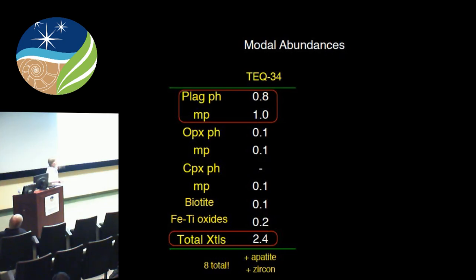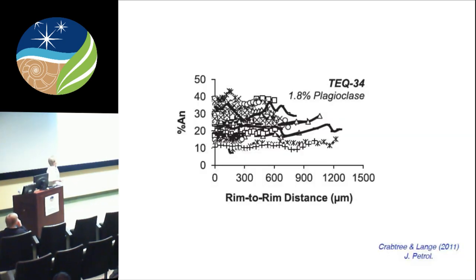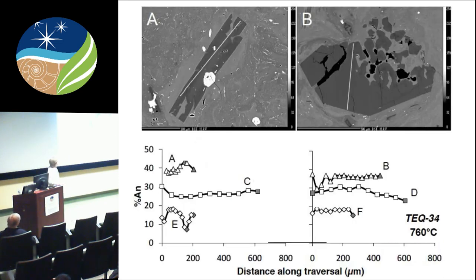And this is what the plagioclase looks like in this sample. So looking at traverses rim to rim, we see anorthite 40, anorthite 10. So that's a huge compositional variation when there's less than 2% plag present. So it's reminiscent of what sanidine's doing in Glass Mountain. And I'm going to just show you the textures of some of these crystals. So an anorthite 40, a nice swallowtail texture. That's what we call a diffusion-limited rapid growth texture. A really strange texture to the right, a little bit more sodic, facets on one side, really weird texture on the other side.